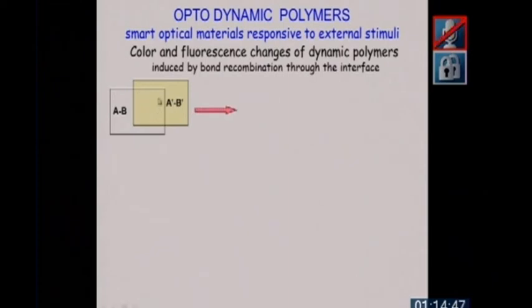You superimpose them, and at the interface where they are superimposed, you should now be able to generate the combination of A with B prime and of B with A prime. A will combine with B prime, and B will combine with A prime. And if this new combination is colored, you will see it. It may also be fluorescent, and you will see it. So at the interface, only where these films are superposed, there will be changes appearing. And if one, I repeat, of these new combinations has a color or a fluorescence, you will see it.